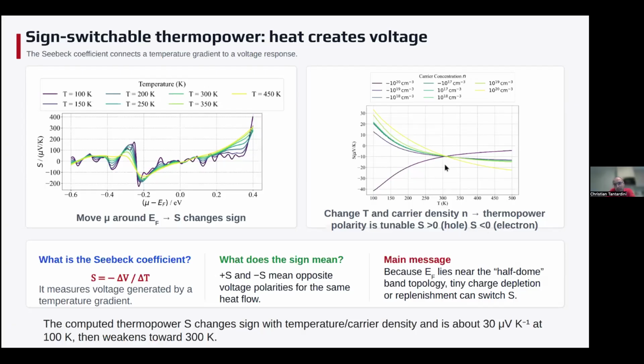In this case, I'm honest with you, the Seebeck coefficient that was found is very low. Usually, to be a good thermoelectric, we should find much higher values. We should maintain, close to room temperature, values in the order of 30 or minus 30. In this case, we simply see that at 300 Kelvin, close to room temperature, there is a change of sign that can allow me to tune this thermopower. But this compound is not, I tell you, an efficient thermoelectric. And this is also reasonable, because when you have a flat Fermi surface, we are not supposed to find a very good thermoelectric. But we have measured and verified this.